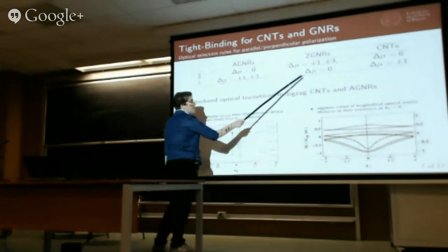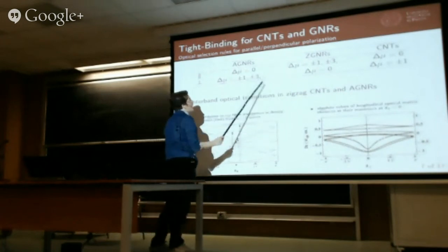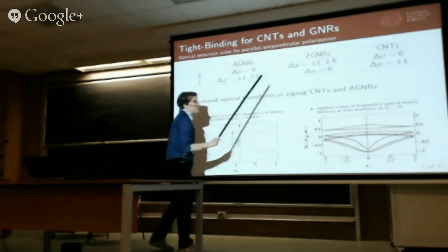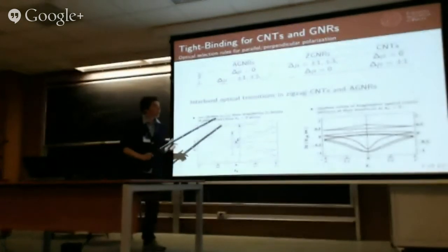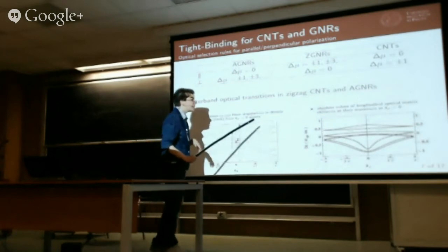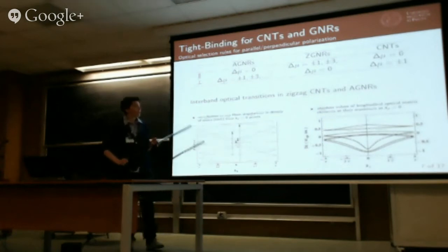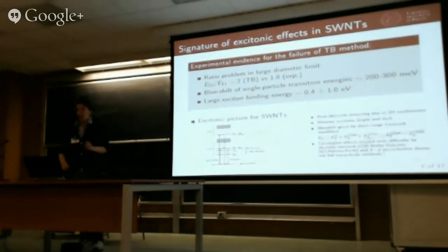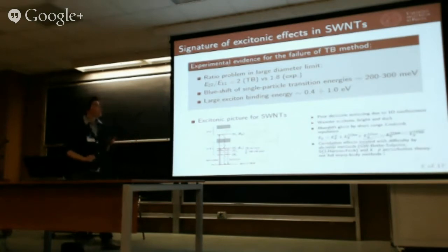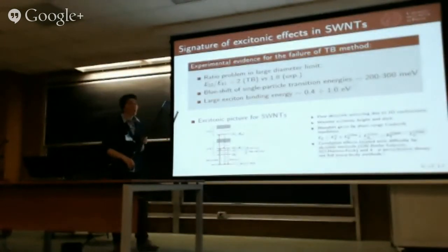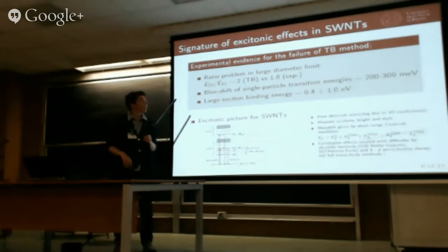Whereas in the case of zigzag graphene nanoribbons, the selection rule related to the polarization of the light is rotated by 90 degrees. So, optical properties are clearly important, in addition to the electronic density of states, for predicting if an optical transition can actually be observed or not in optical spectra. So, we can say, generally speaking, that the tight binding method is able to predict both electronic and optical properties of graphene-based systems with a qualitatively good agreement with experimental data.